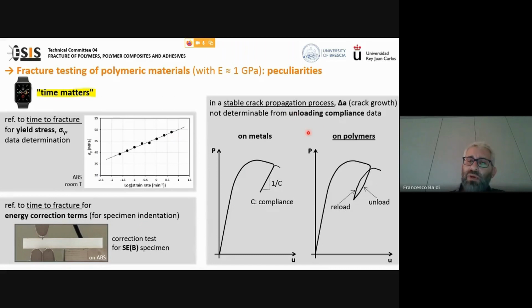Another thing that I would like to point out is that in a stable crack propagation process, which is typical of polymers, the crack advancement is different from what happens in metals, in the sense that in metals, during a stable crack propagation process, I can determine indirectly the crack length by measuring the unloading compliance. With polymers, it is not possible, since the polymeric response depends on the time and on the history, and the unloading curve and the reloading curve are not superimposed.